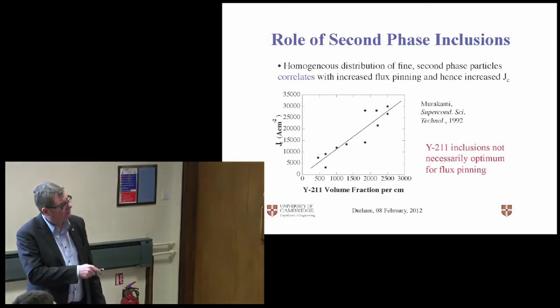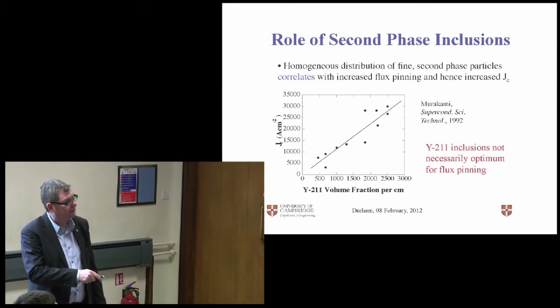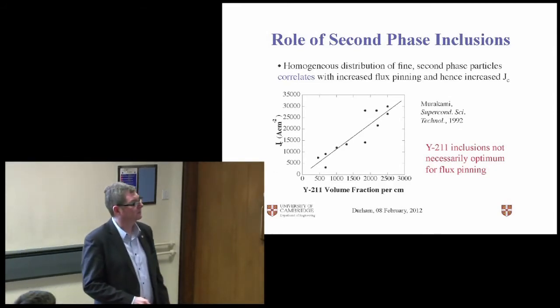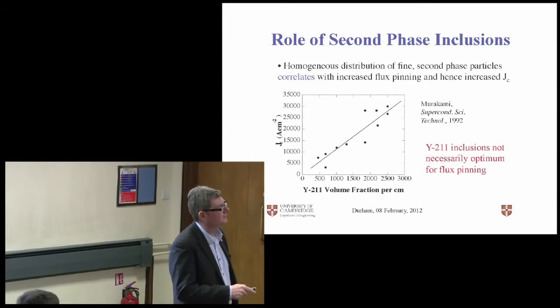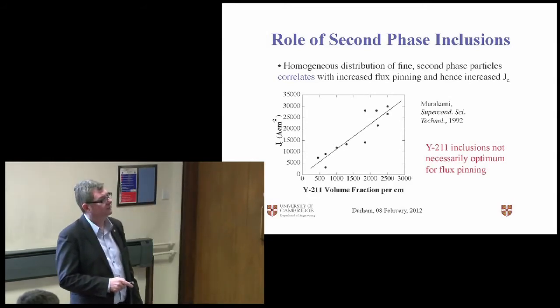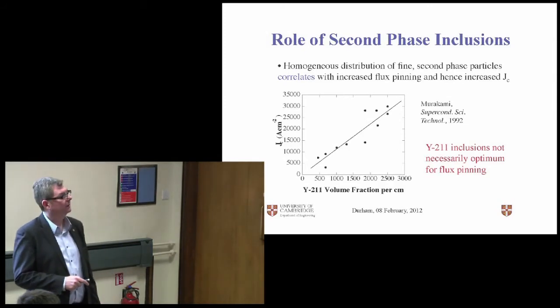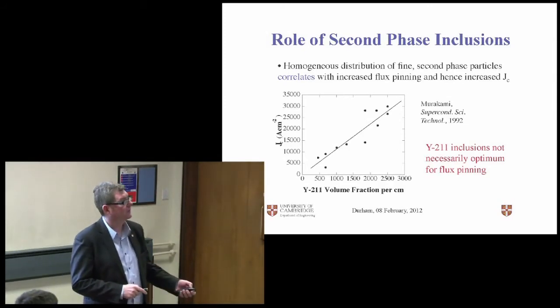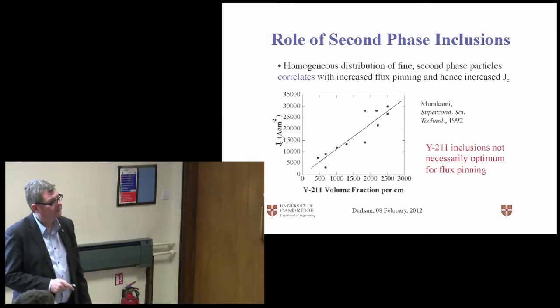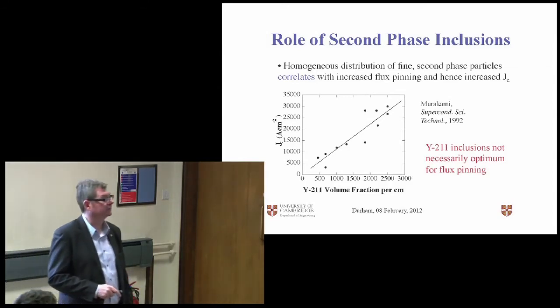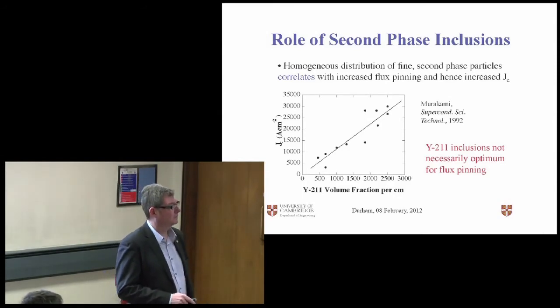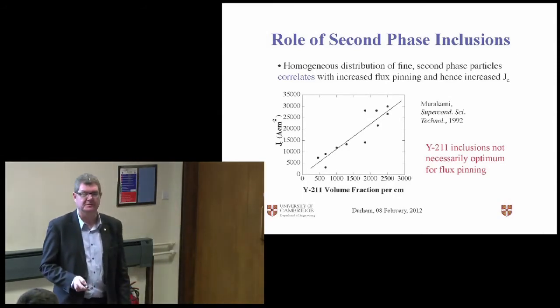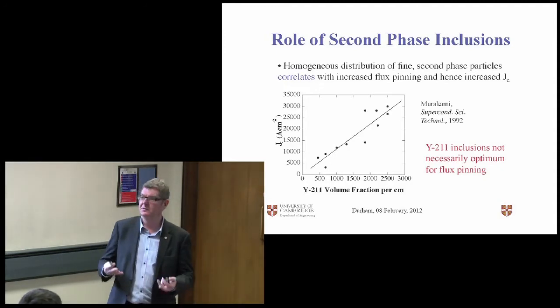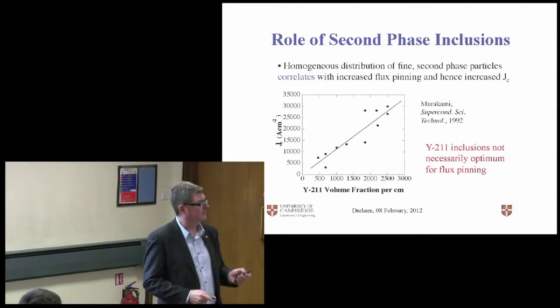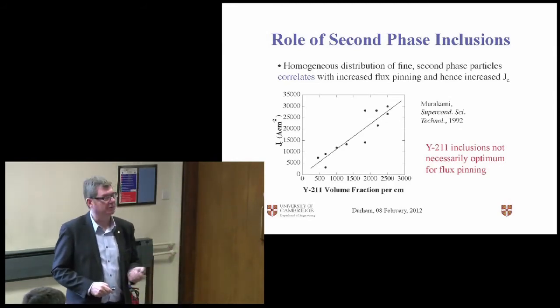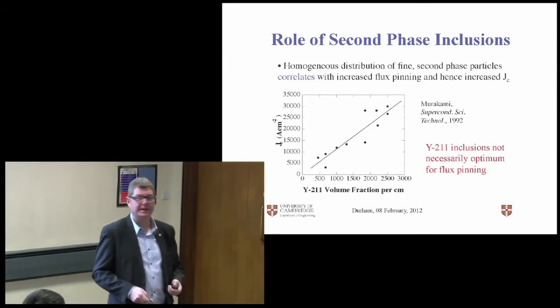And we thought that because if you look at how critical current density varies with the number of these particles you have in your sample, you see that JC increases roughly linearly. So that suggests that Y-211 is forming a very effective pinning site. However, it necessarily doesn't form the optimum flux pinning site. And I've got to say, for a decade, we were obsessed with making Y-211 particles smaller and smaller and smaller to get higher and higher JCs. And we'd actually missed the point, and part of this talk will be to explain how we missed the point.